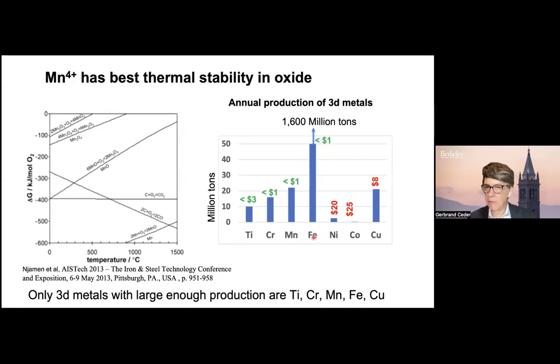Iron is great in polyanion systems where the voltage is reasonable. If you use the iron 2 to 3 redox couple in a close-packed oxide, the voltage is too low, so you'd have to use 3 to 4, which tends to lead to a high amount of oxygen redox. So that leaves you basically with chromium and manganese. Chromium is a wonderful element. It's cheap. It has multiple redox states. You can make fabulous cathode materials with chromium, but there's certainly a societal and industry aversion to chromium because of the toxicity of chromium-6. If that could be overcome or managed, I should say, chromium is really a leading element for making probably the highest energy density cathodes you can imagine.